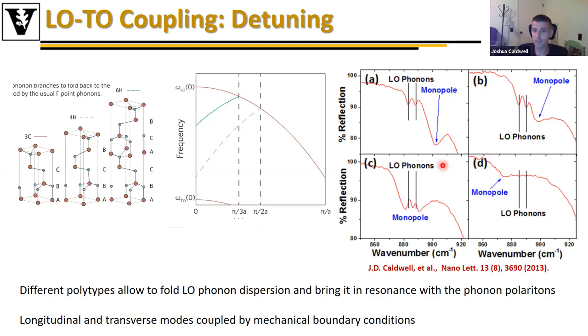But one of the interesting things that we observed was that as we shift one of these phonon polariton resonances towards this mode, the amplitude of these zone folded LO phonons that we ordinarily would not observe becomes much stronger, until they spectrally overlap and we see a strong coupling phenomenon where the spectral frequencies of these zone folded modes become a drop in absorption, right? So they become forbidden transitions until it propagates through and then the strong coupling is lost.